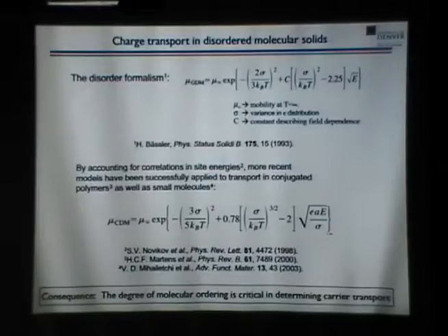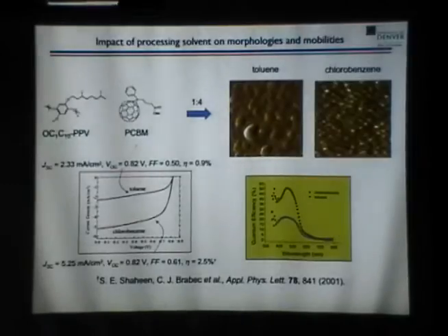So that's actually can be a good thing for organic solar cells because now the velocity of the carriers actually gets better at higher temperature. In fact, their performance tends to be better at 50 degrees centigrade than at room temperature. Okay, so what is the impact of all that morphology stuff? That means the way we process the materials and the way we make the films will be critical in determining